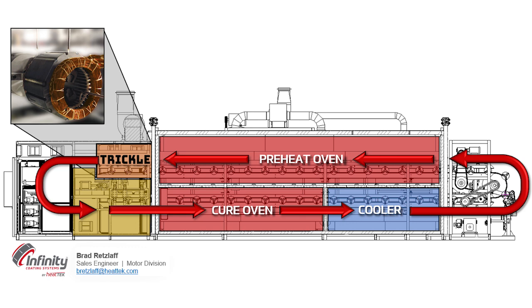These positions will likely have different nozzle placement, ID, OD, cuff paper, center, and end of conductors in order to achieve optimum slot fill and resin penetration. It is important to note that the E240 will not appear to smoke upon the initial trickling of the resin, nor will any detectable odor be present in the trickle or bake zone, as the E240 is a zero VOC material. The typical smoke and odor noticed with a polyester resin is due to the volatilization of the monomer.